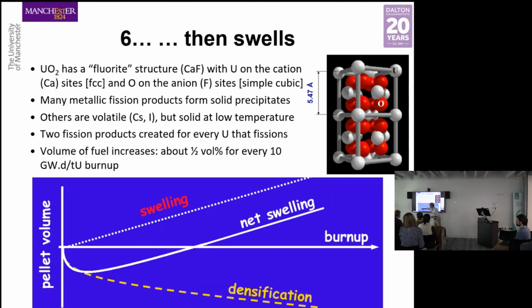So here we're plotting the pellet volume, that's where the pellet started, and we've got these two competing effects going on. One of them is causing shrinkage, and that's this densification process. So the pellet is just getting denser and denser and denser. But that process starts quite quickly and then levels off and becomes almost flat. Why do you think that happens? You know the answer. I'm not even talking to you.